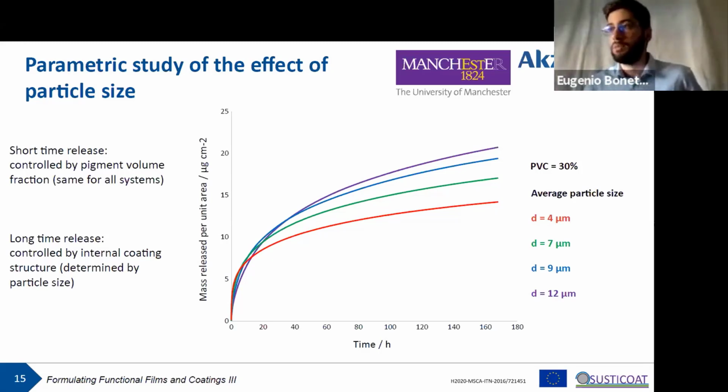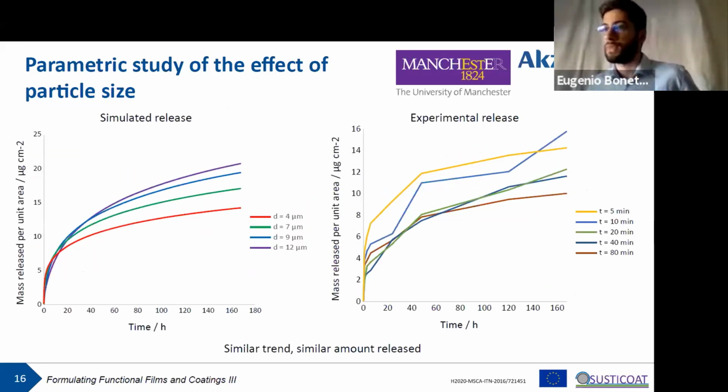However, the long time release is controlled primarily by the diffusion through the cavities left after the dissolution. So the long-term release is controlled by the particle size, basically. And comparison with experimental data again shows similar trends. So decreasing the particle size results in a decrease in the leaching. And in this case, also the amount released is similar, at least in the same order of magnitude.